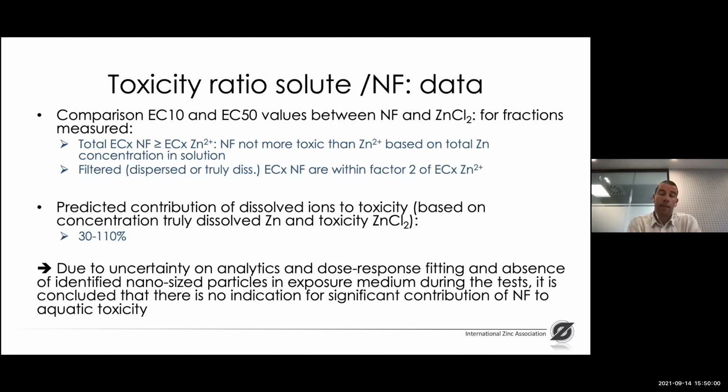So there's quite some uncertainty on analytics and on dose response fitting, and also the absence of identified nano-sized particles in the exposure medium during the test. Therefore, we concluded that there is no indication for a significant contribution, and significant is important because we will not say there's no contribution of the nanoforms to the aquatic toxicity, and that in fact the majority of the effects can still be explained by the presence of the ions.